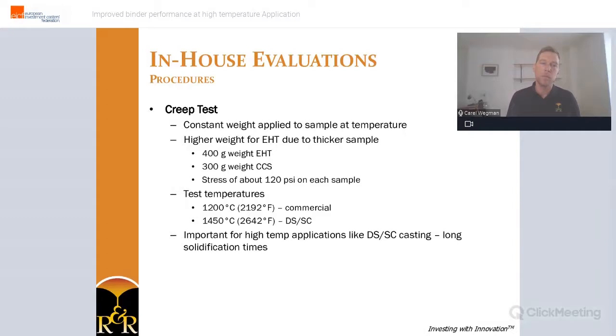The creep of the shell was considered important for high temperature applications like directional solidification and single crystal, since the alloy remains molten for a long period of time and exhibits a force on the shell. And samples were tested to monitor how this deflection was progressing as a function of time under a constant weight and a constant temperature. 2 weights were chosen, 400 grams for the EHT sample and 300 grams for the CCS sample. Because the EHT sample was generally thicker than the CCS sample, different weights were chosen so that they translate in about the same level of stress on the sample.